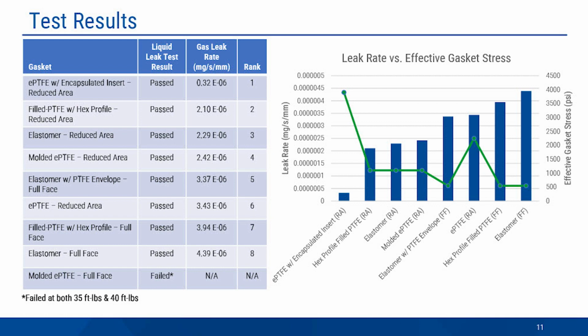So unsurprisingly, the only true, I say true full face gasket that wasn't an elastomer is the only one that failed. So the molded ePTFE, again, has a much lower minimum gasket stress than even expanded PTFE, but even with that, in a standard full face design, it failed the liquid leak test at both 35 and 40 foot-pounds. For those asking, it did leak from all 3 flanges very slightly. It wasn't spewing, but any sort of leakage is a failure.